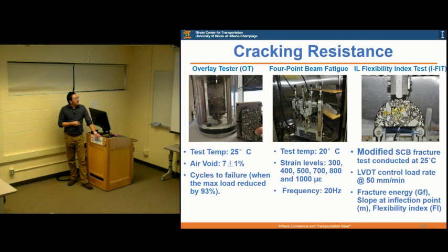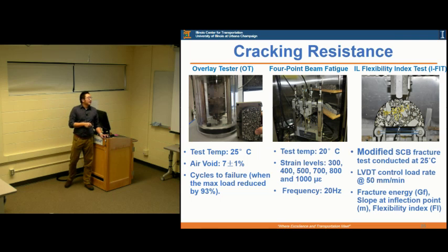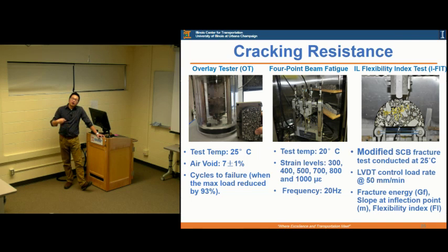We also have cracking resistance tests. We ran three different kinds of cracking tests: an overlay tester, a beam fatigue test, and an I-FIT test. They use different devices and different parameters, but the temperature is pretty much at room temperature, 20 or 25. For example, if you look at the overlay tester, we use cycles to failure to categorize the cracking resistance. If you look at beam fatigue, we also use cycles—how long your material can withstand that under different kinds of loading.